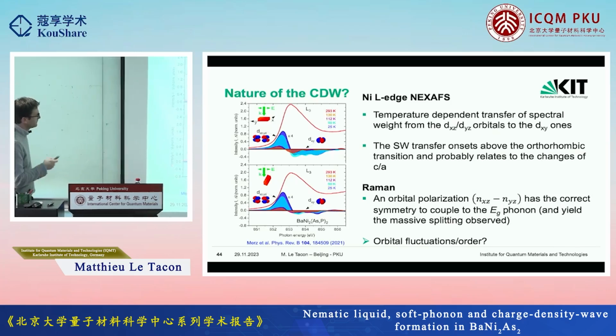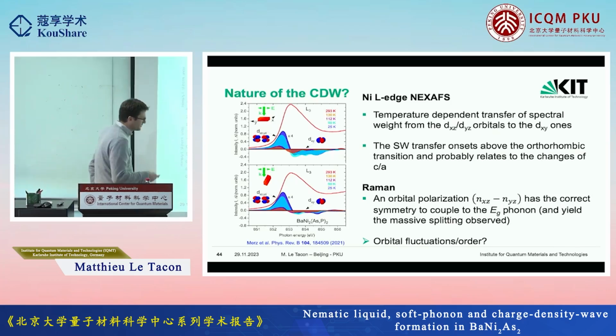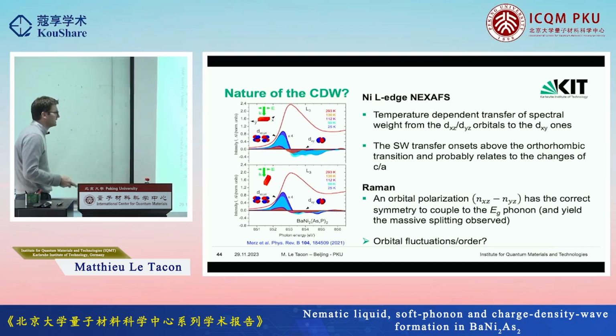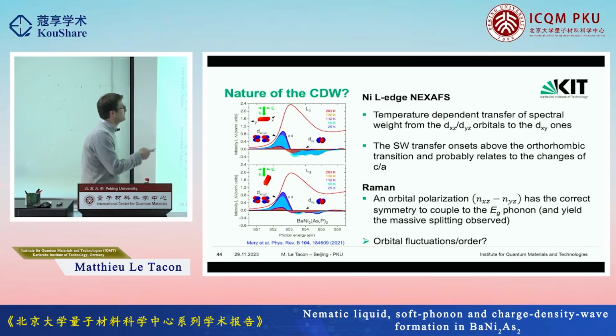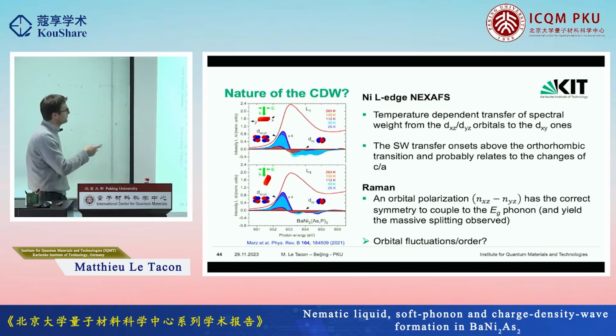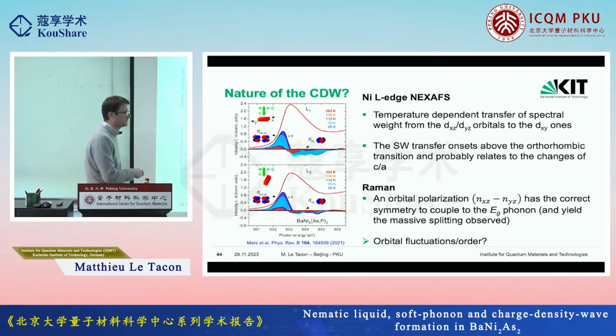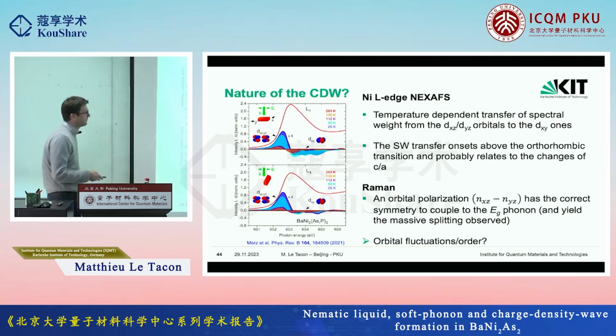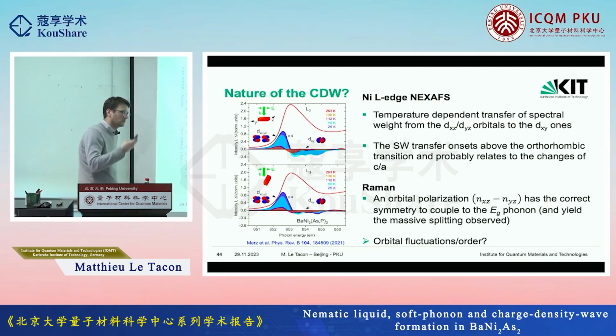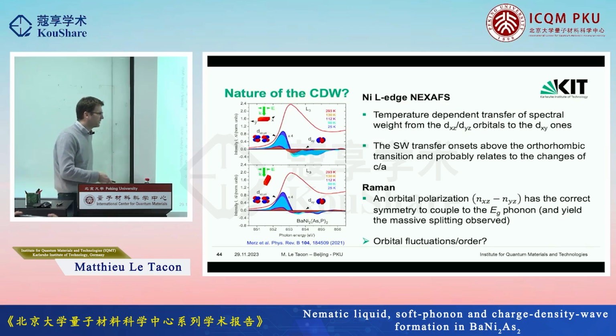I just finished on that. We have more than these speculations, actually. We do have some evidence that indeed the orbital degrees of freedom are playing a role, from our early X-ray absorption data. If you look at the dichroism of the X-ray absorption, the polarization dependence as a function of temperature, what you can find is that there is a spectral weight transfer between the in-plane and the out-of-plane orbitals, which is associated with the formation of the charge-density wave. That basically indicates that what we call in that case a charge order is probably more of a funny manifestation of an orbital polarization in this metallic system.